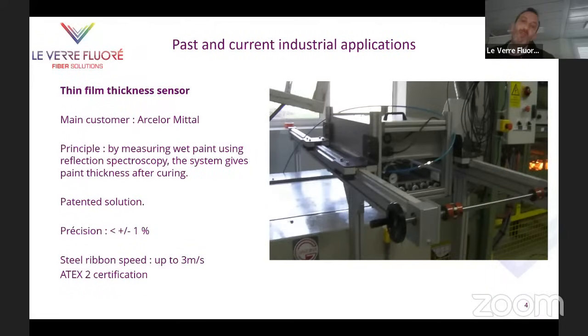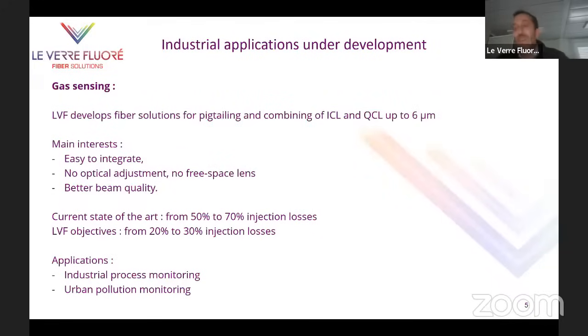It's a patented solution. We've got a typical precision of 1%, which is large enough for the needs of companies such as ArcelorMittal. It's an industrial use, with steel ribbon speed up to 3 meters per second, which is significant for the coil coating industry. And it's in an explosive atmosphere environment, so the system has been certified ATEX. Actually, it's the only time Verre Fluore supplied a complete system. We no longer commercialize this because we've got much better to do with our fibers. As a conclusion, it's a relevant, proven technology that works, but we no longer do business with this device.